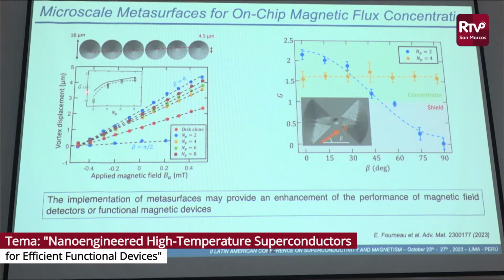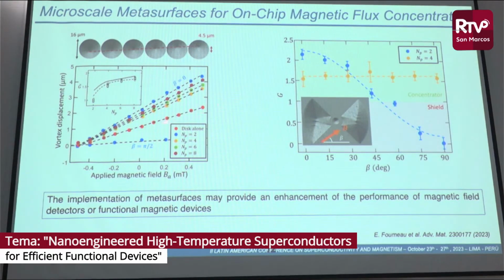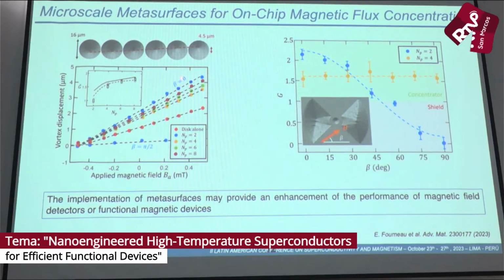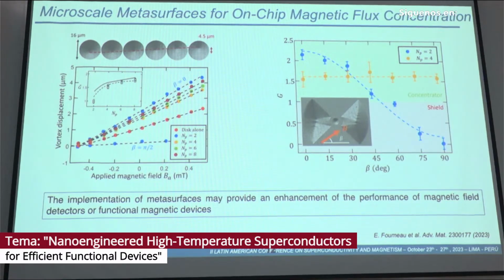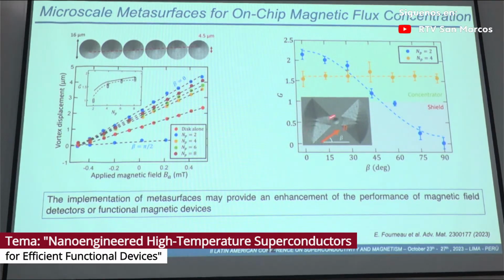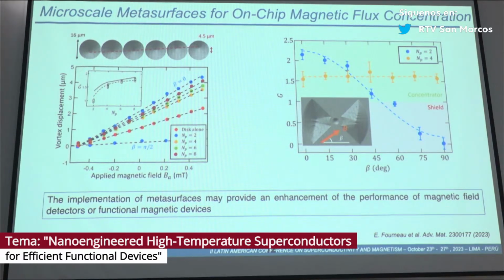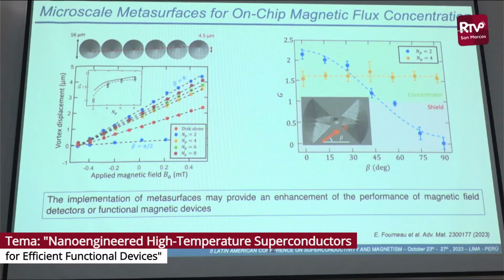And these are the experimental results. What we have done is to image, by using magneto-optics, the position of this central vortex core. And by tracking the position of this core as a function of the applied field, we see that without the concentrator, we have a displacement which is much lower than in these data points here where we use the concentrator. So by playing with the concentrator geometry, we are able to improve the magnetic field inside the core of this concentrator, and we see that this is completely isotropic and can be used in order to provide an enhancement of the performance of different detectors or functional devices like energy harvesters, for example, that can be placed inside of these structures.